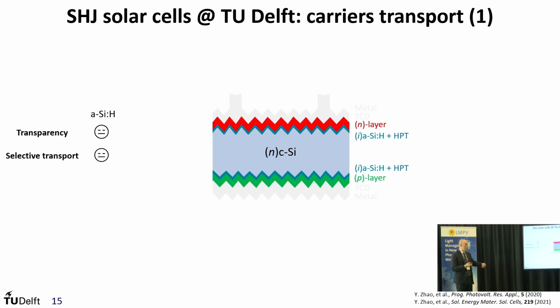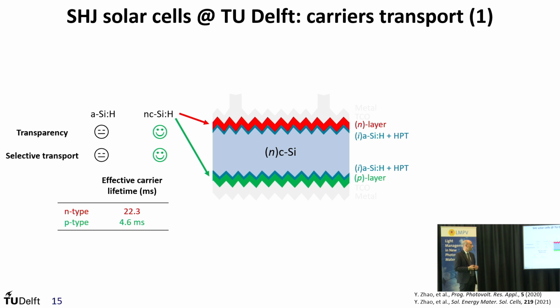So, following from the modeling side, we started to develop nanocrystalline silicon or nanocrystalline silicon oxide that ultimately, in addition to the initial passivation that was only of chemical nature, now because of the doping concentration as well, especially in case of N-type, we could keep also in check the passivation with also the added electrical field component of passivation. With the N-type based symmetric samples delivering more than double the initial lifetime.